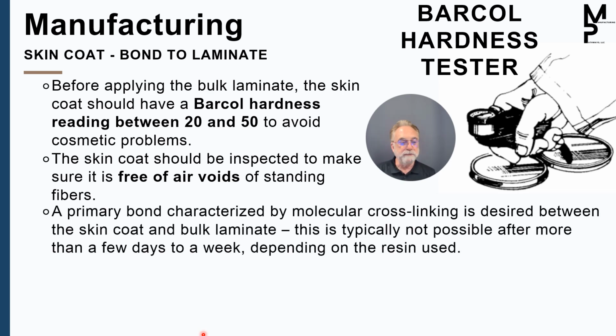So in the world of polyester, we have a neat thing going on called primary bonding. And when you walk into the boat factory, you get that beautiful smell of styrene. What's going on there is the material doesn't fully cure. It really takes probably a month to fully cure. But in the first few days, there's a lot of bonding going on. And what this lets us do with boat construction is it lets us put that coating in, put the chop strand mat in, let that cure, and come in with another layer and subsequent layers, structure, without having to do sanding and surface preparation, because there's still chemical bonding sites.